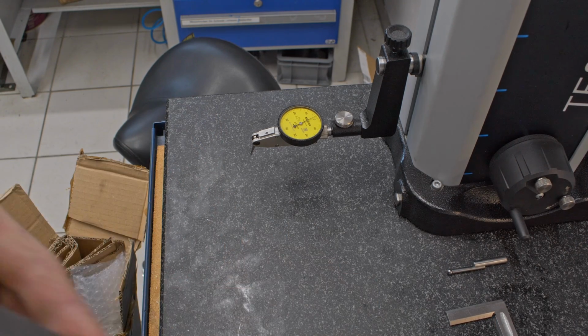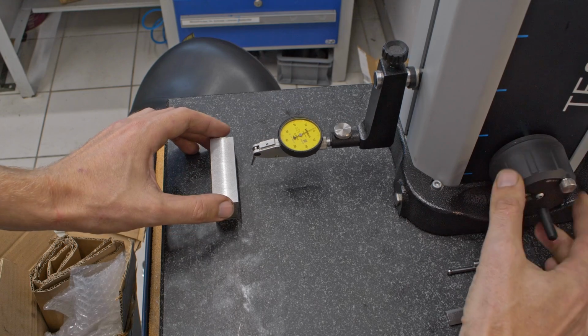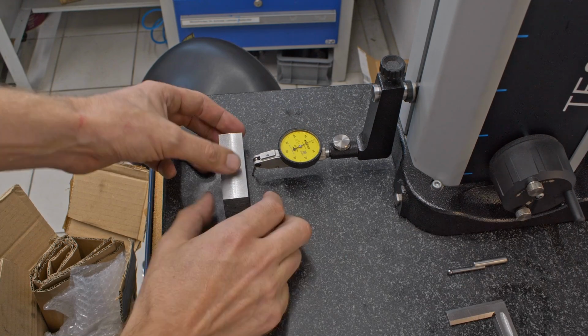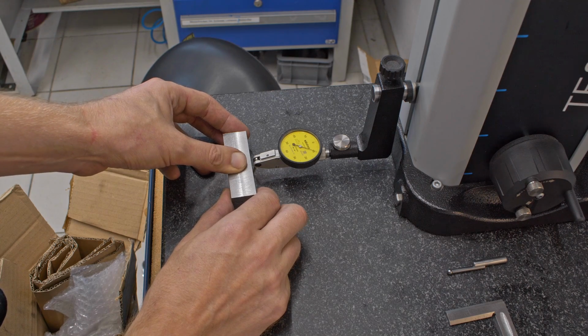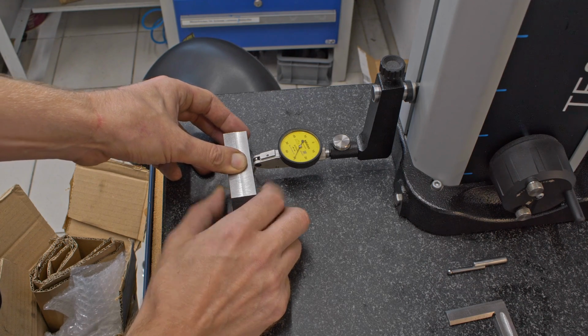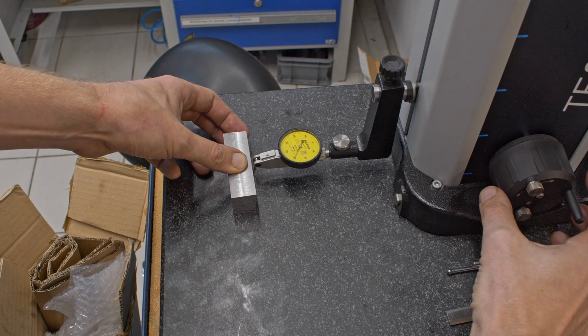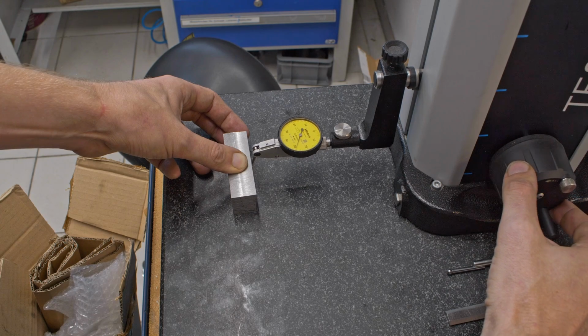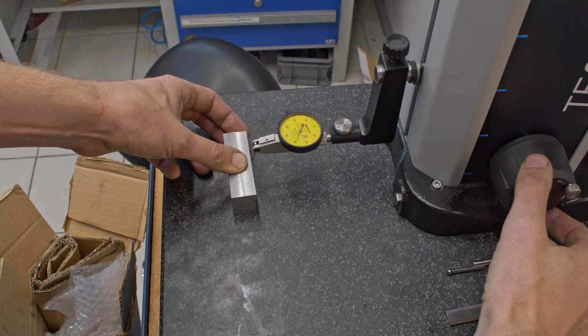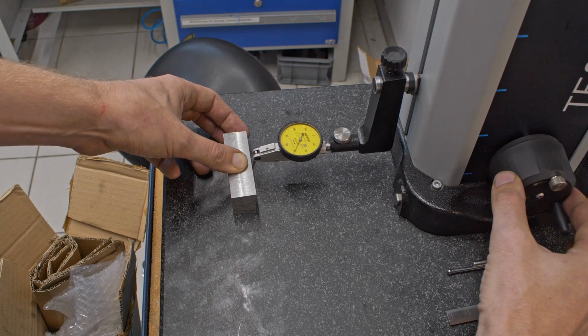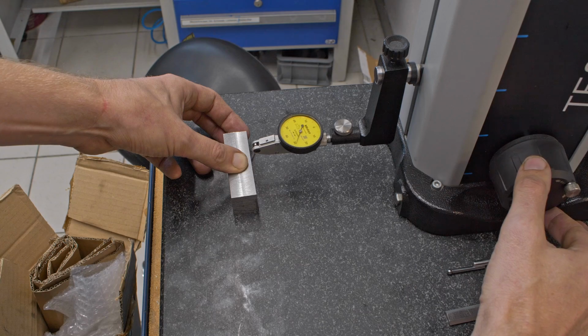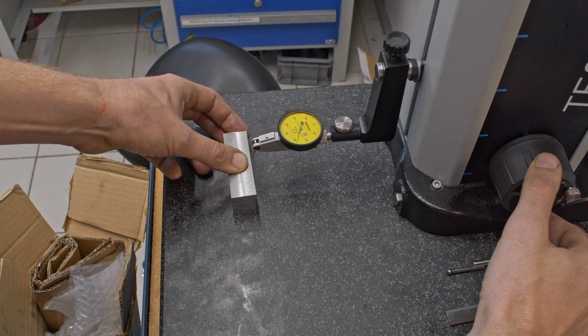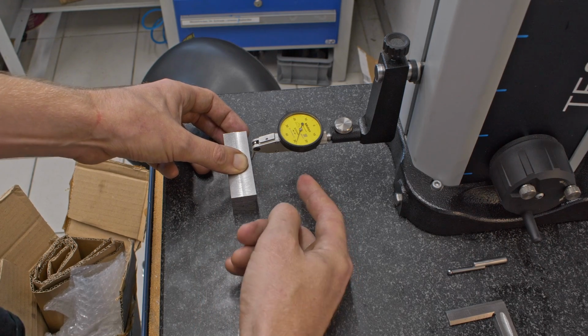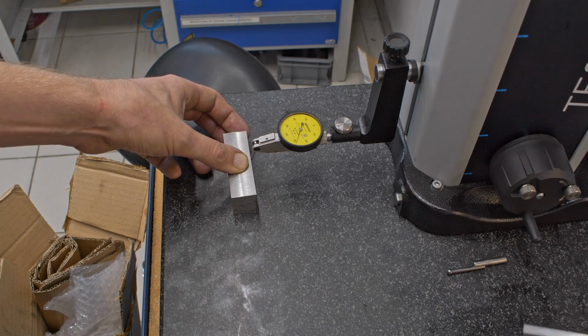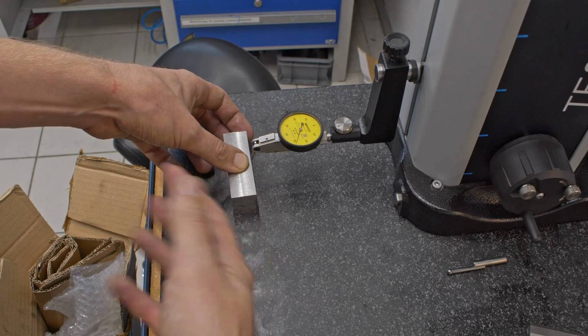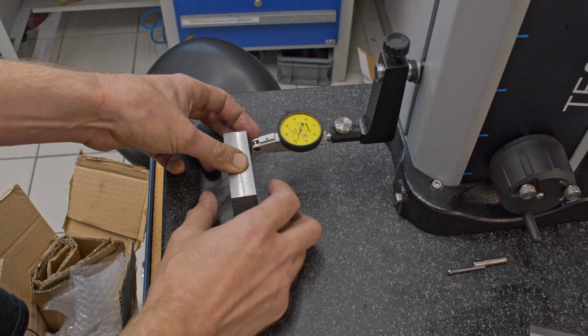And the way this works is we make sure everything is clean and seating well on the surface plate. We bring the dial test indicator down all the way. We move the work up against the dial test indicator to a convenient number, like 30. Then we just traverse the work by using the height elevation of the measuring slide. And this is well within 10, 15 microns, well 20. It's falling off to the side here, which we also qualified using the knife edge square. So those two, the measurement and the visual observation that we did, match up, which is always very nice.